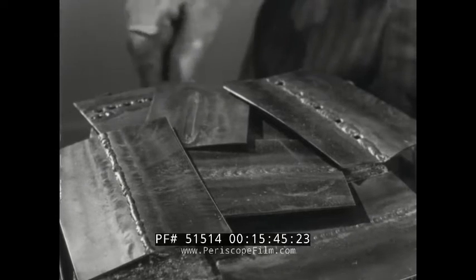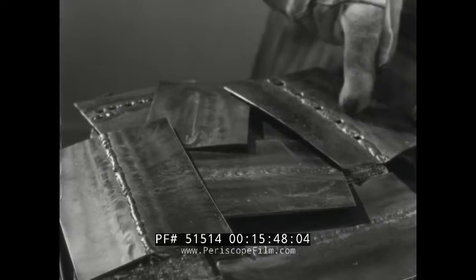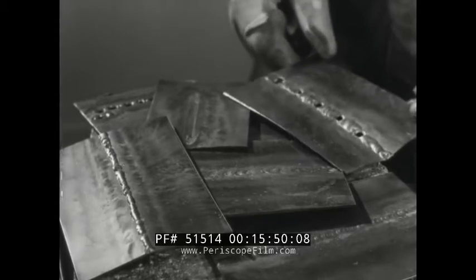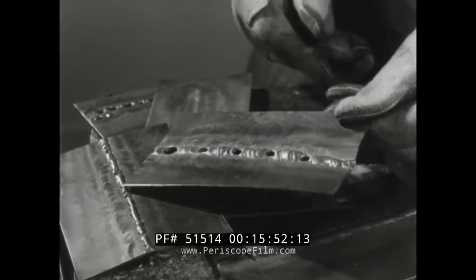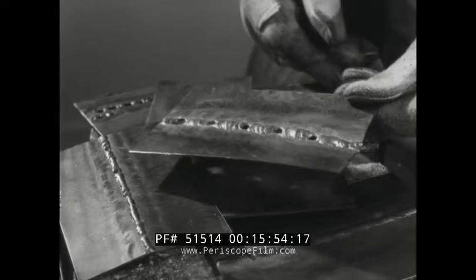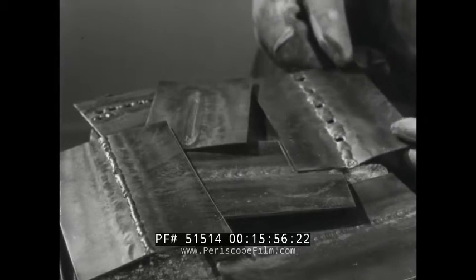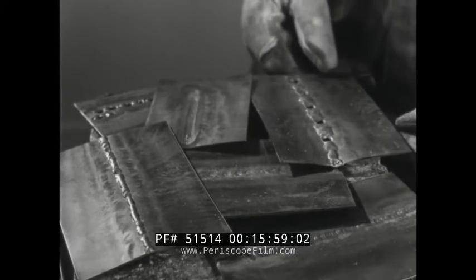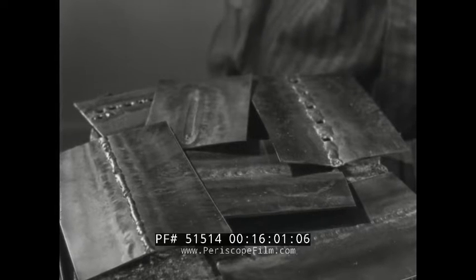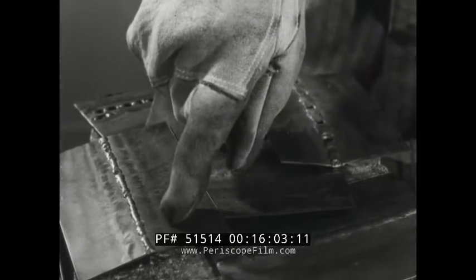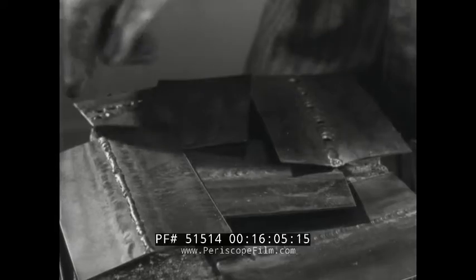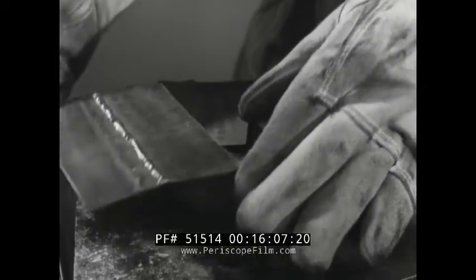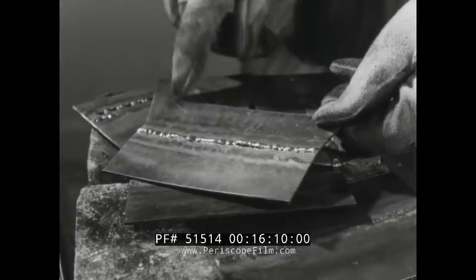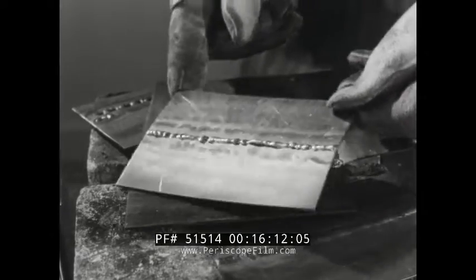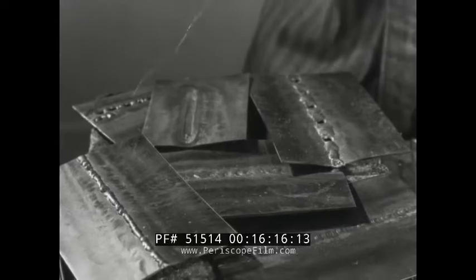This bead isn't good. In fact, it's lousy. Look at the holes. Burned clear through the sheet of steel, and the rod was melted so fast that its metal spread over too much area. These are all results of using too much heat on the base metal. And here's an example of a weld that wasn't heated enough. As a result, the rod was melted and dropped onto comparatively cold base metal. Welds that are heated too much or too little won't have much strength.